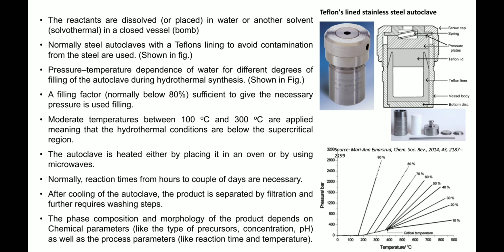At a particular temperature and certain pressure, there is a possibility that the iron or carbon diffuses into your material. So in order to use it multiple times and to avoid contamination of impurities in the synthesis products, the Teflon liner plays an important role. It is essential to use a Teflon liner during hydrothermal synthesis of materials.